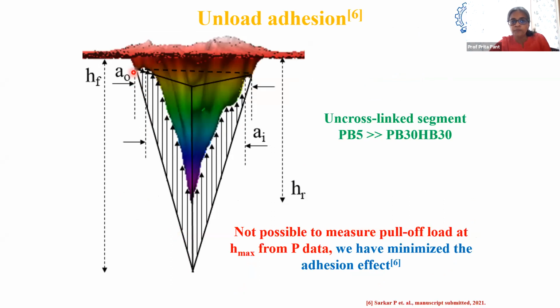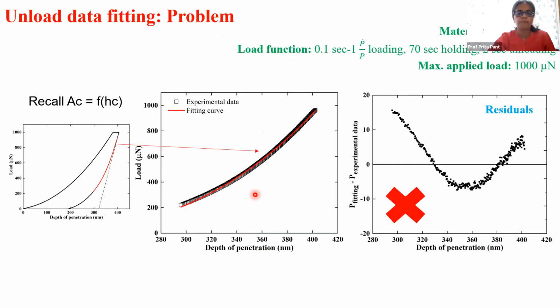So here is a side view. And what we feel is happening is the tip went in till here. And as we pull it back up, there is all this pulling that happens. And when we finally yank it out, this would have been the profile of the tip when it was all the way in, and all of this convolution that is happening is because the surface is getting pulled up a little bit when we pull the tip out. Okay, so I'm not going to go into details of this. It doesn't have any bearing on the story that I'm telling you today, but again, factors that do play a role, and may, depending on what you are after, need looking into.